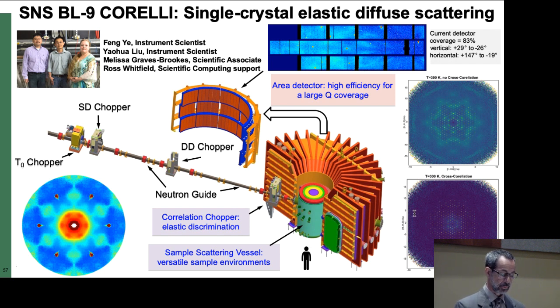The CORELLI instrument, as already mentioned, has this correlation chopper, which allows elastic discrimination. It's dramatically shown here with the two diffraction patterns on the right. At the top here is Benzil total scattering, and below it is the elastically discriminated pattern. You can see almost all the diffuse scattering disappears because it's all due to phonons.